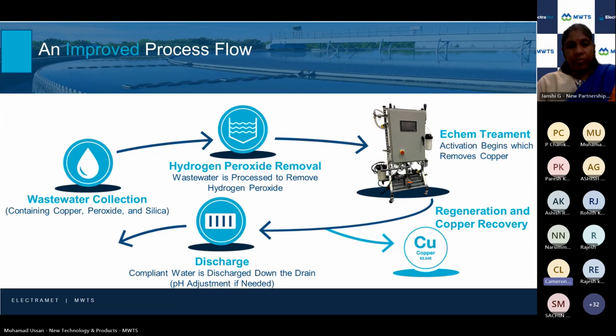So putting this complete process flow together for the wastewater at a fab facility, you still have to handle the solids and the peroxide because they can negatively impact the electrochemical treatment. But the key benefit of electrochemistry versus ion exchange is that if there is residual peroxide, it will not destroy our media. Hydrogen peroxide will decompose ion exchange resin. If hydrogen peroxide enters our system, it's just a modest inefficiency that it creates. We'll use the energy to break down peroxide instead of removing copper. So through a combined process, we can develop a more efficient system.